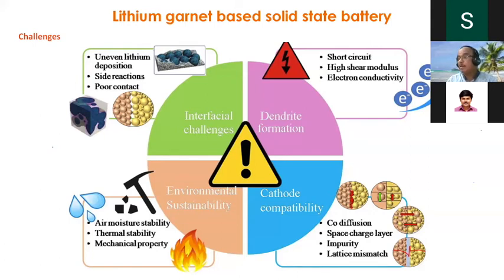Still, we thought that solid ceramics would block the lithium penetration, the dendrite. And still, I could see through the grain boundary, I could see the needles forming, and short circuit takes place. High shear modulus and electron conductivity, several things people started to understand with the dendrite. And cathode compatibility is a much bigger problem: diffusion of the cathodes, the reaction product layer and space charge layer, impurities, and lattice mismatch. We thought that ceramic processing is easy, but garnet also started to give trouble. Moisture stability is poor, and the thermal stability, the mechanical properties, so many problems. After finding a suitable material, we still had big technological drawbacks, and how to overcome them one by one.